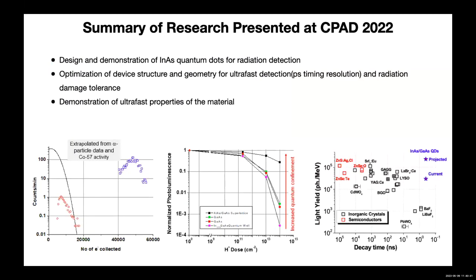Here is the summary of the work I presented in CPAD 2022. I won't go into much detail due to the time constraint, but in short, we work on indium arsenide quantum dots embedded in a gallium arsenide, aluminum gallium arsenide superlattice structure. We have demonstrated optical properties like ultra-fast decay time, high light yield, and better radiation hardness, which are required in detection technologies for high-energy physics. In addition, we have also demonstrated detection of alpha particles and gamma rays using this material.